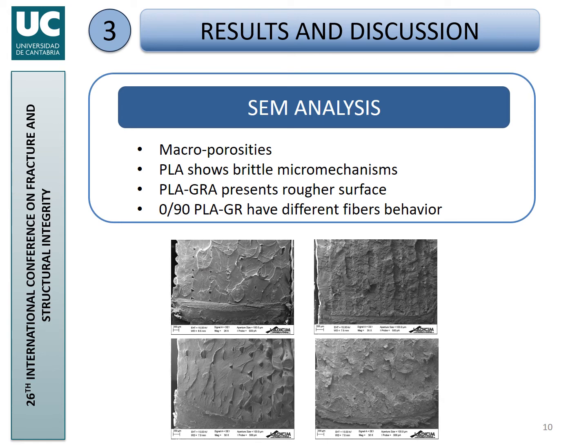We made also, as mentioned before, a SEM analysis, and these explain the previous results quite straightforwardly. When we analyze the 45/-45 material, which are these figures below, we may observe that there is a change on the fracture mechanisms from these brittle ones to this other more, let's say, non-linear, a much more rough surface in all the filaments for the 45 and the -45 filaments.